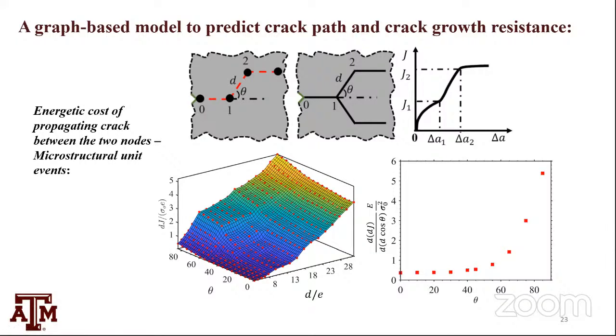Well, with the finite element, no. With this directed graph model. It seems to me that you are basically finding the path that the crack will take in order to fracture the specimen, right? So what happens if the crack actually doesn't fracture the specimen and stops somewhere in between? Do you have that built into the model, that the crack can at some point not choose to make a jump anymore? Not until the microstructure. I see your point, and it does happen in circumstances. In this case of predicting the model, unless the microstructure tells it don't grow, it's got to grow.